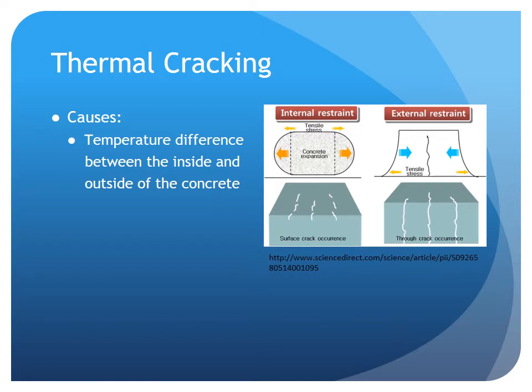Heat of hydration increases the internal temperature of concrete, creating a thermal gap between the inside and outside of the structure. This thermal gap causes tensile stress as a result of the restrained condition of the inside and outside of the structure. Thermal cracks occur when the tensile stress reaches the tensile strength of the concrete, as shown in the figure.